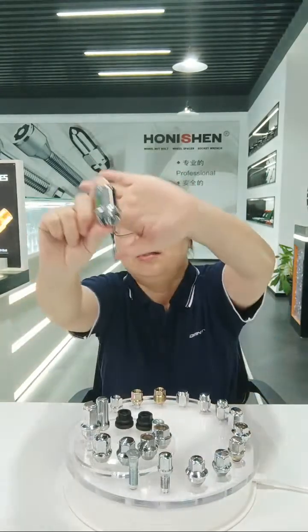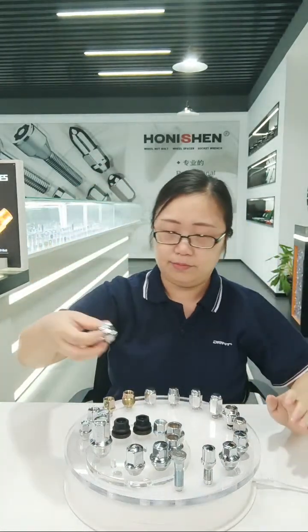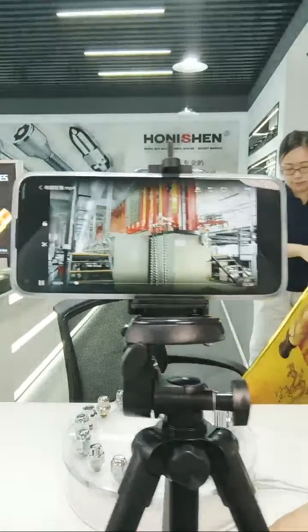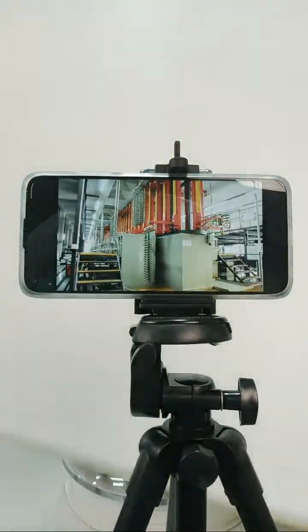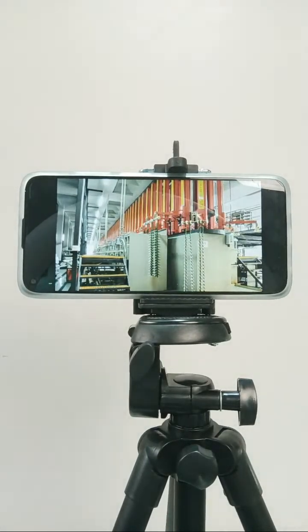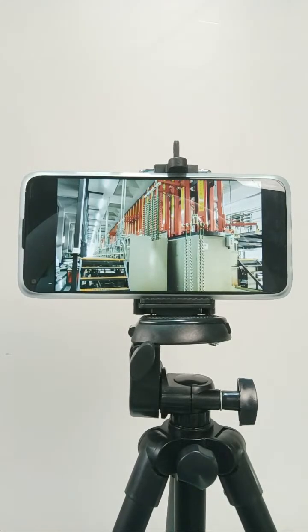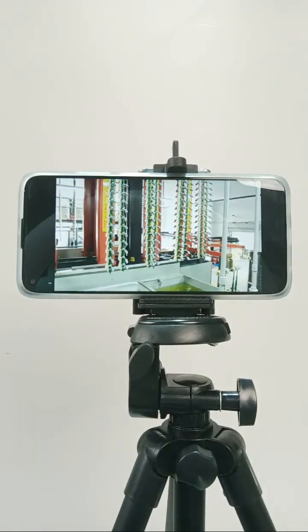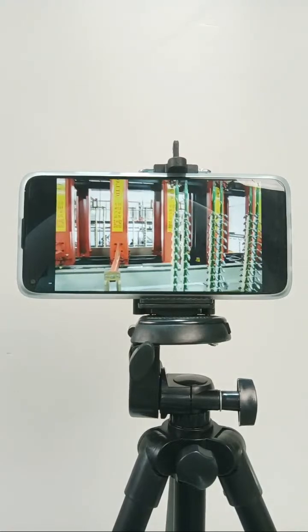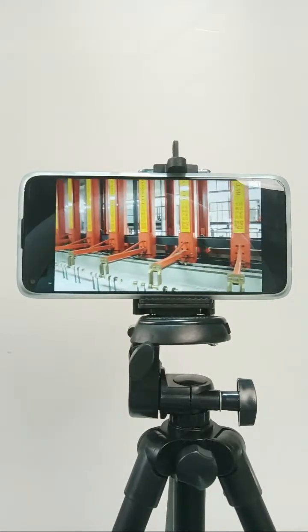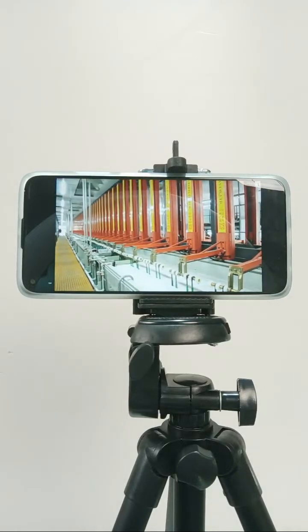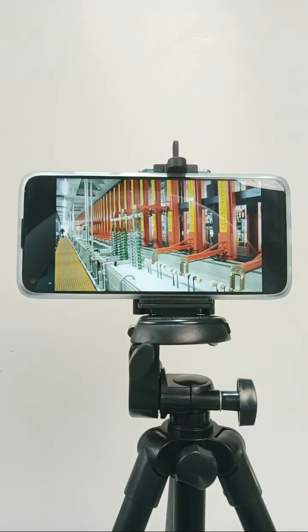And this is our chrome finish. For our chrome finish, we have our own electroplating production lines, and we have 2 chrome and 2 black chrome. Now let me show you our electroplating production lines. Electroplating quality is our pride. Only our factory has an independent electroplating production line. We usually make 3 layers of nickel and 1 layer of chrome, and control the anti-rust performance of the product by detecting the thickness of the nickel layer and the functional difference between each layer.